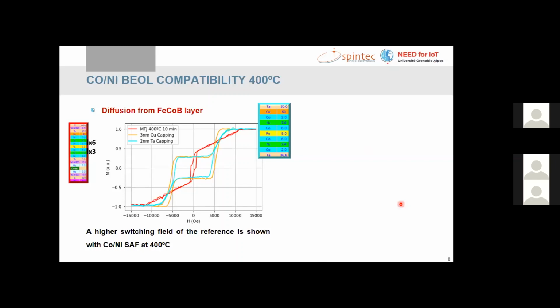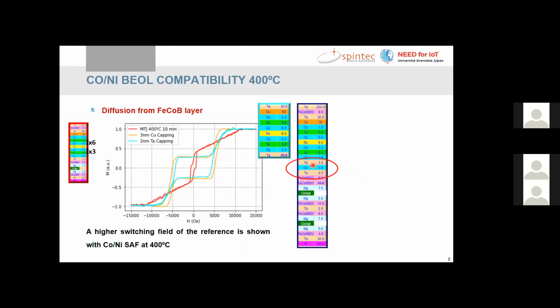So the only problem we had is that when annealing this structure at 400 degrees, which is a typical temperature required for CMOS compatibility, the coercive field of these layers decreased very much. And we started to look for the reason for this and some possible solutions. We observed that when having a capping layer of tantalum or copper, we did not observe this decrease of coercivity. And then we tried to find some solutions, and we made a double tantalum getter barrier, where this tantalum is normally used as an absorber of the boron, so that it will not migrate to the MgO barrier, but will be absorbed by the tantalum lamination. And so by making this double composite lamination, we have been able to improve the annealing tolerance of the cobalt nickel SAF, and even at 400 degrees, the coercivity remained quite high.